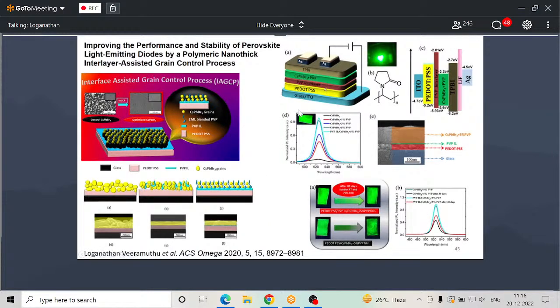And this is another paper we published. In this case, we are using some interlayer strategy. Why do we need this kind of interlayer strategy? Because we know that PEDOT:PSS is a hole injection layer they always use. And the hole injection layer is going to corrupt your emission layer, the perovskite layer. So in order to avoid that, we use some interlayer and we tune those layers.